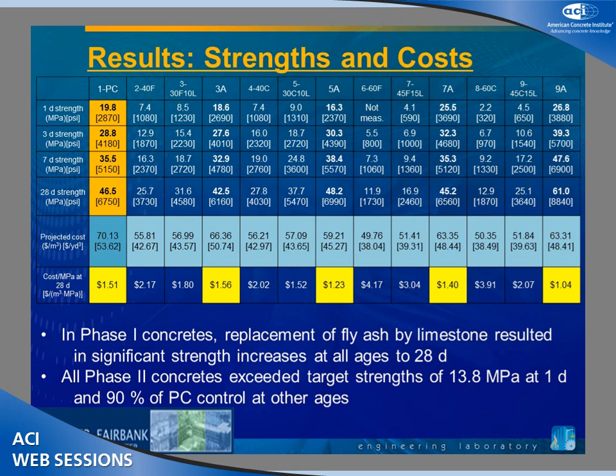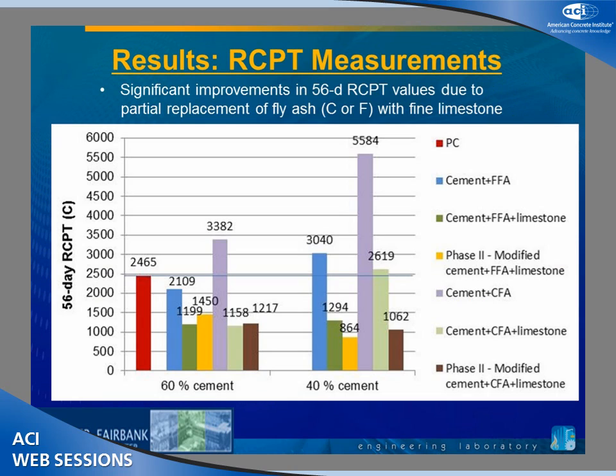So to get equivalent strengths, you can see that 3 of the 4 Phase 2 concretes are definitely more economical than the initial concrete, and the other one is basically a wash, $1.51 versus $1.56 in terms of meters cubed per megapascal. Strange units, but you can just compare the numbers. So these concretes are very economical because the fly ash is much cheaper than the cement. The limestone powder is somewhere in between the two, so overall you can save some money.